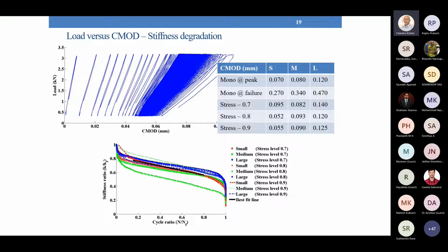are quite large. Now, in a fatigue test at 70%, 80 and 90% of the stress ratio, we see that these are the displacements, and these crack mouth opening displacements are in the range of the monotonic at peak. You see these values. So all these values are in a similar range as that which takes place in a monotonic test at the peak. So again, this can be used as a failure criteria under fatigue. That is the crack mouth opening displacement at the peak load in a monotonic test, which could be used as